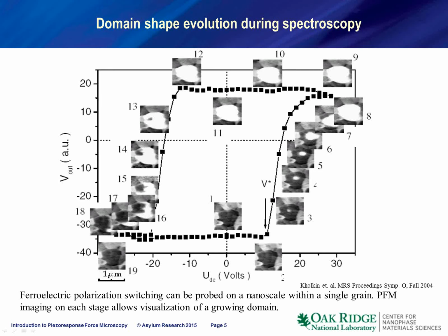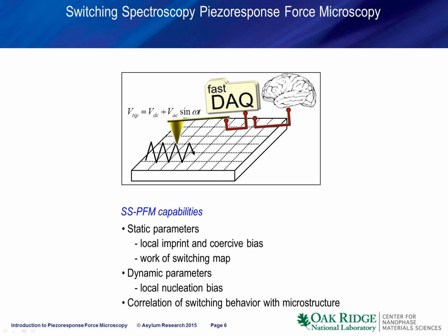And the answer is, one hysteresis loop is actually not enough. What we can do is acquire a hysteresis loop at each point on the sample surface, an approach that we refer to as switching spectroscopy PFM or SS-PFM. In this case, we park the tip at one point on the sample surface, measure the hysteresis loop, shift the tip to another location, measure another hysteresis loop, and repeat this process until we perform hysteresis loop measurements on a grid of points on the surface. So we acquire a three-dimensional data set comprised of the hysteresis loop at each location.